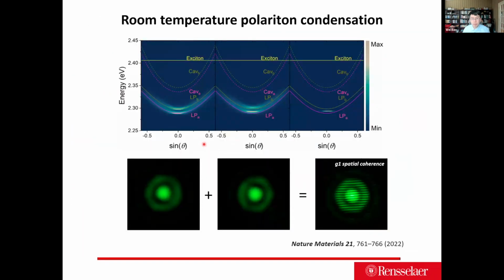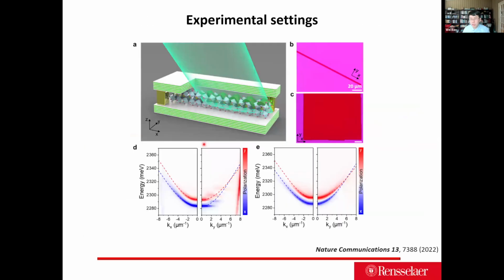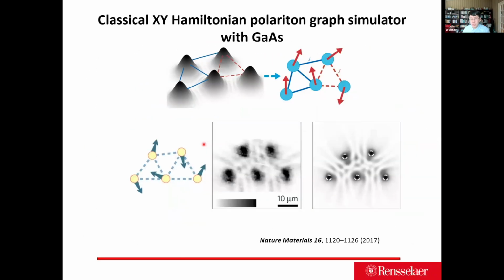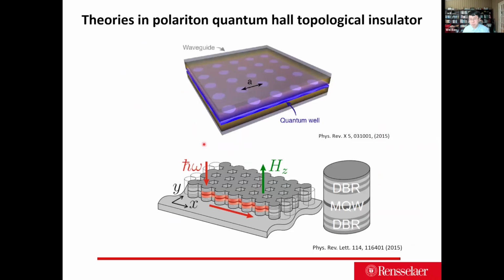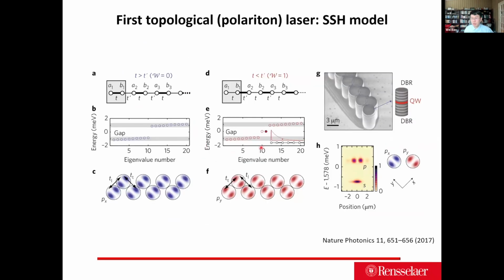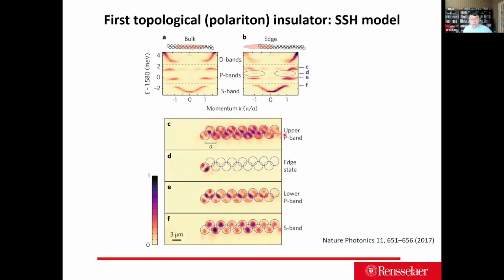Yeah, you can see in Professor Jacqueline Bloch's experiments, this is the whole pillar array they make. So you can count 1, 2, 3, 4, 5, 6, 7. You only need 7 pillars along one line and then the other 7 pillars on the other line. So that's all their samples. And each of the pillars is about 3 micron in size. So you don't need a large sample. But etching this deep is challenging.